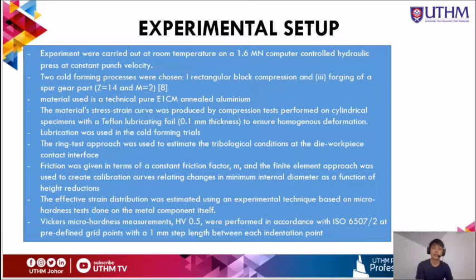The ring approach was used to estimate the tribological condition of the die-workpiece contact interface. Friction was given in terms of a constant friction factor, M, and the finite element approach was used to create calibration curves relating changes in minimum internal diameter as a function of height reduction.